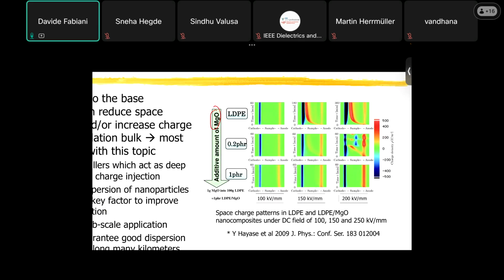And as you can see, a nanofiller of magnesium oxide is put inside the insulating material. Without magnesium oxide, increasing the electric field, you can see a lot of heterocharge accumulation during time. While with 0.2%, you see that this heterocharge accumulation is reduced by increasing the field, and with 1% of magnesium oxide, you see that it is completely suppressed, also at very high field.